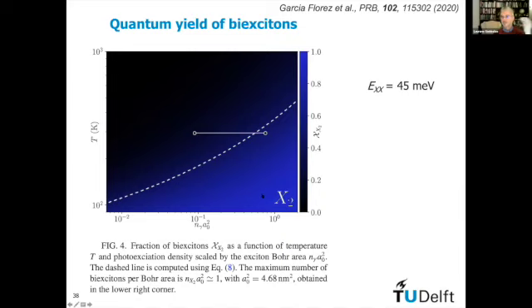And we would like to do such measurements in the future, and we can distinguish between the single excitons and the biexcitons, because the biexcitons have a smaller polarizability than that of two excitons. So if two excitons bind together to form a biexciton, the polarizability and, as a consequence, the imaginary conductivity should go down. Now that's something for the future.